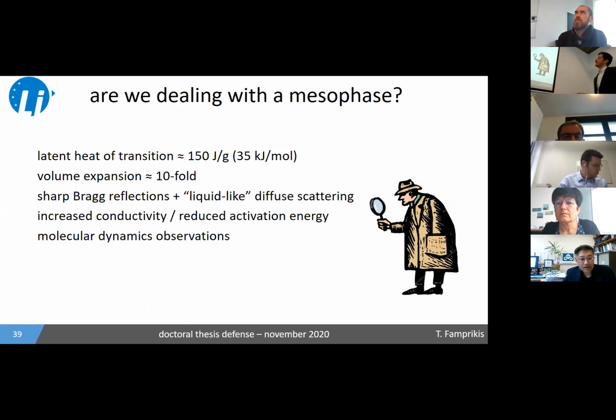We have here a latent heat of transition that is quite high, of the order of melting, more than a phase transition. We have a large volume expansion. We have the combination of Bragg reflections and liquid-like diffuse scattering, a vastly increased conductivity and reduced activation energy. And the most direct proof of all is the molecular dynamics observations.